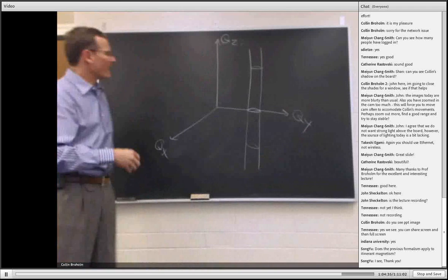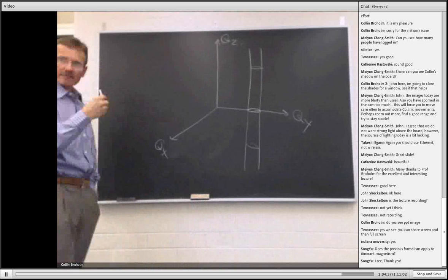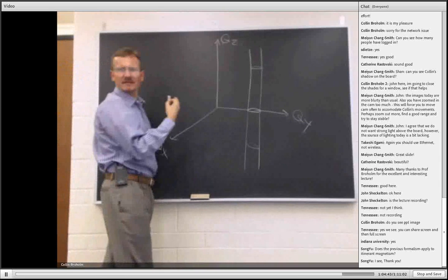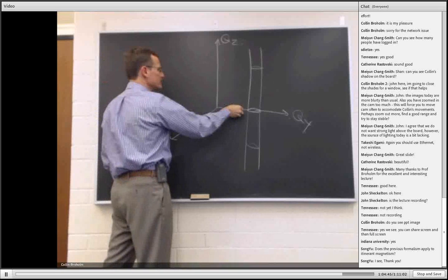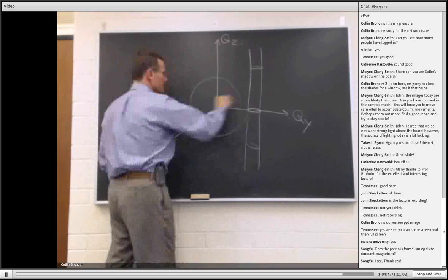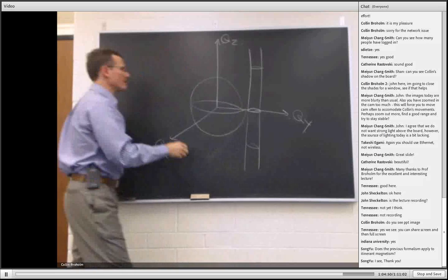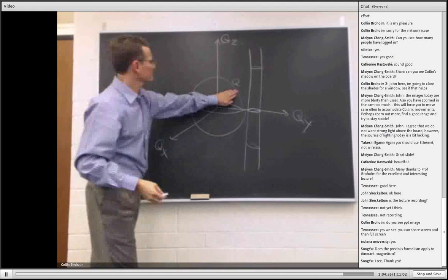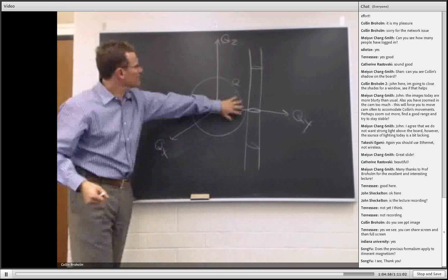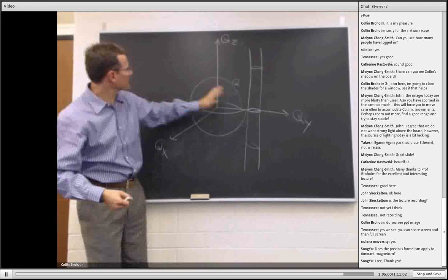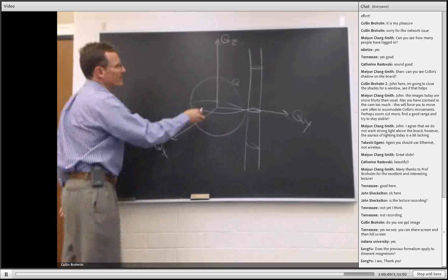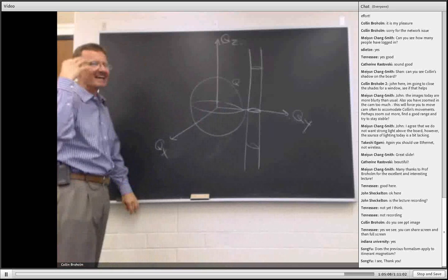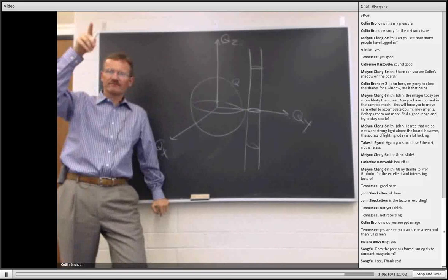Now, what happens when I'm dealing with a powder sample is that I'm not going to be measuring this beautiful pattern in the three-dimensional momentum space, but I'm going to have to average over a so-called Ewald sphere. So I'm always going to be measuring, as I change the length of momentum transfer, the intensity which lands on this sphere. And so at small momentum transfer, maybe you can keep in your mind's eye that little pattern of diffraction that I showed you.